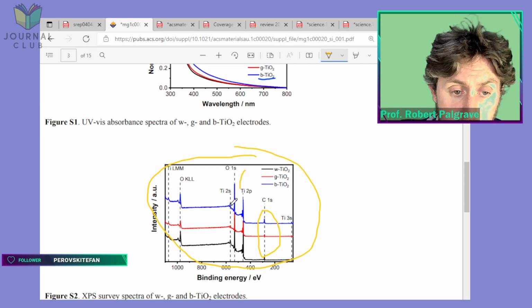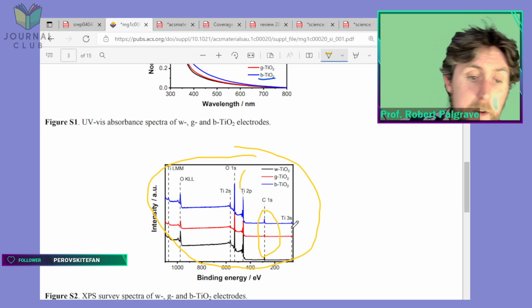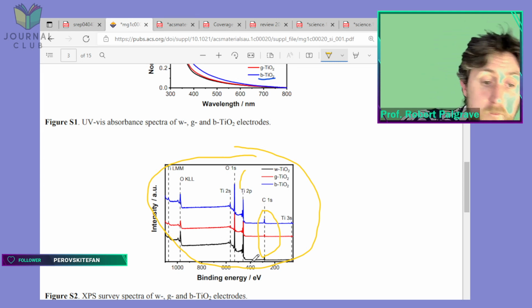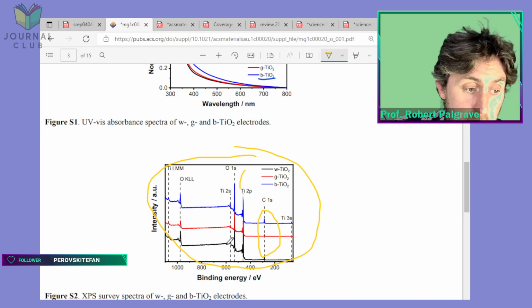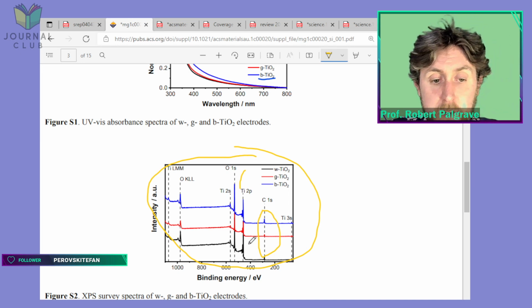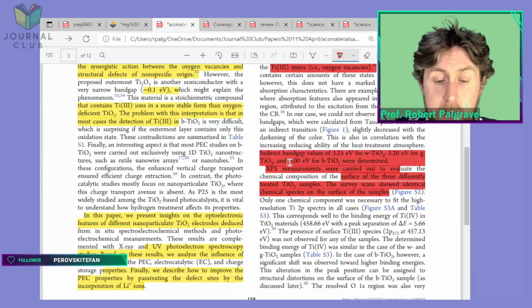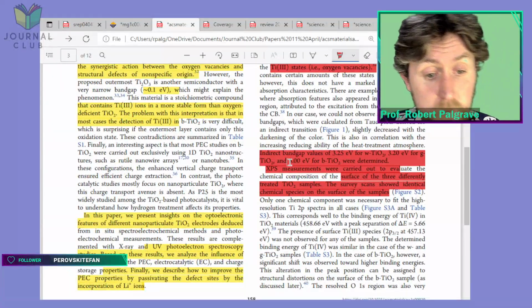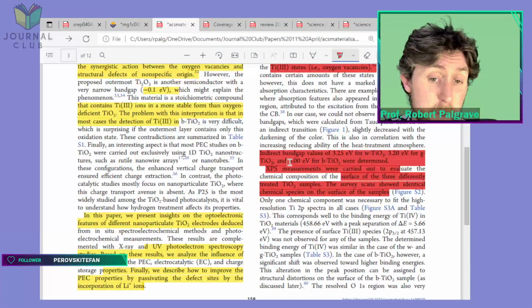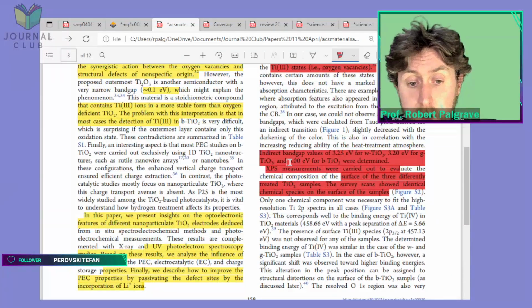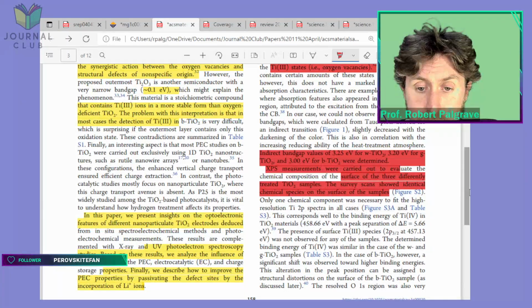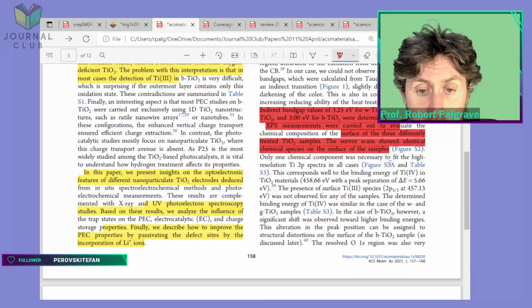There are other peaks that arise from titanium: an oxygen Auger line here, titanium 3s. So broadly speaking, there aren't any extra elements that have appeared during the treatment process, either the white or the grey, the grey or the black, which makes sense. You wouldn't really expect any extra elements to come in when you just heat it up in hydrogen. One thing I should say, XPS can't really detect hydrogen, so we're not able to see hydrogen. There may be a lot of hydrogen in the black TiO2, but we won't be able to detect that using that technique. So they also look at the high resolution titanium 2P spectra.